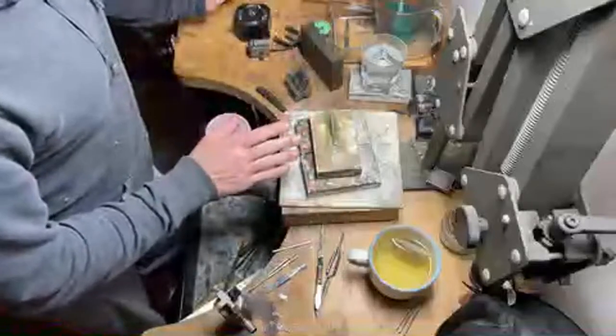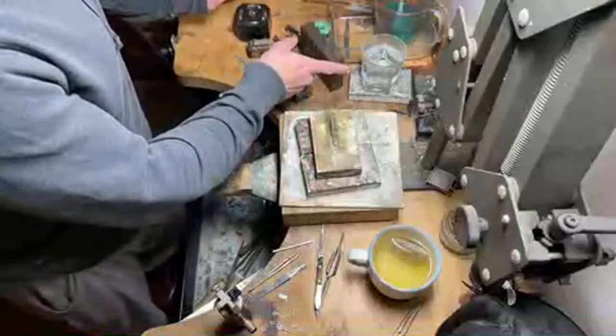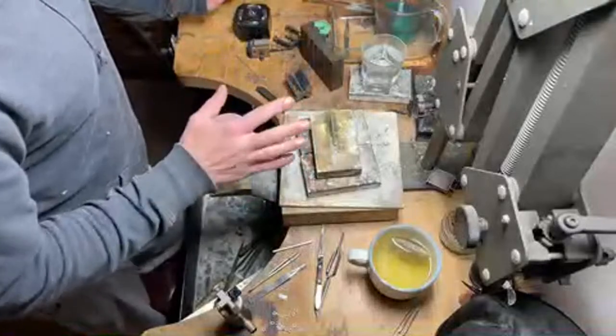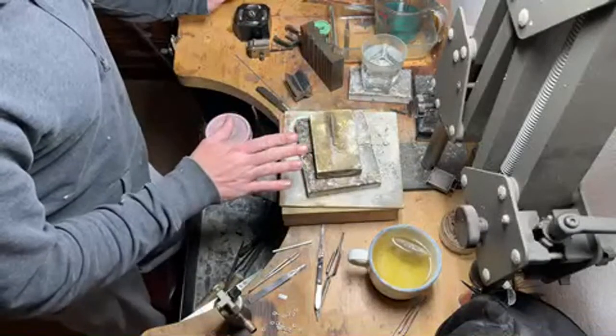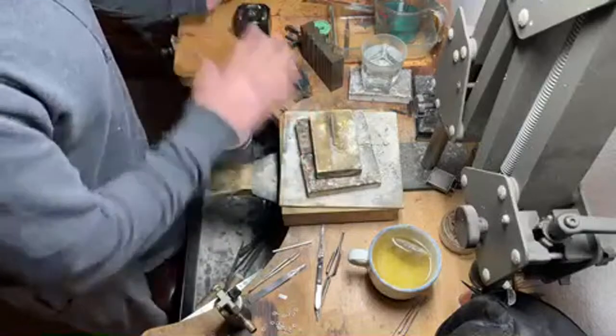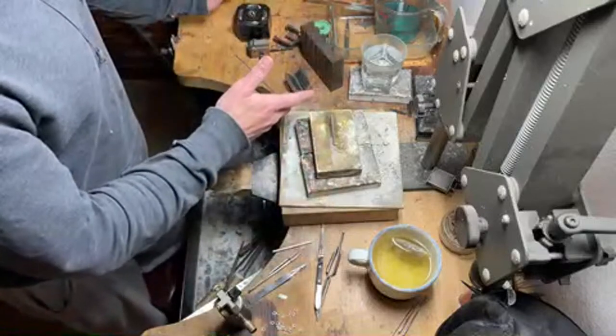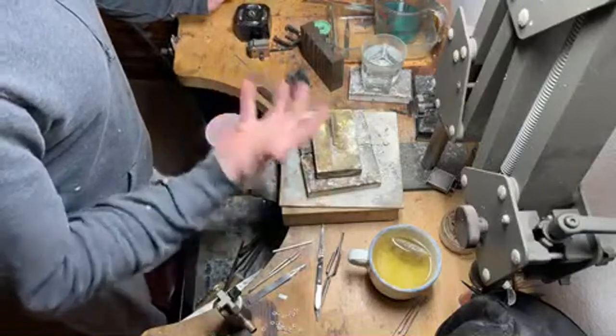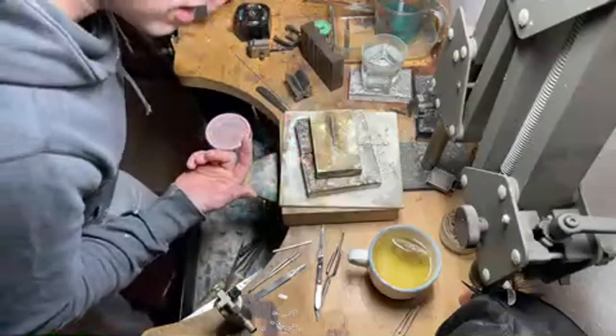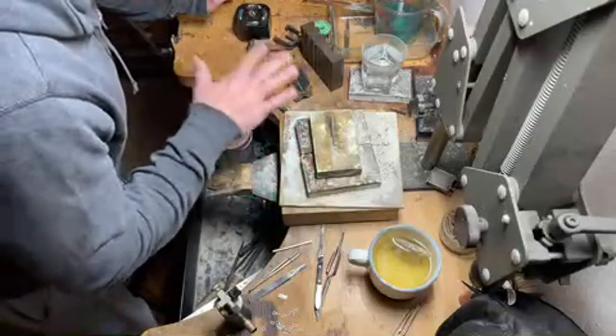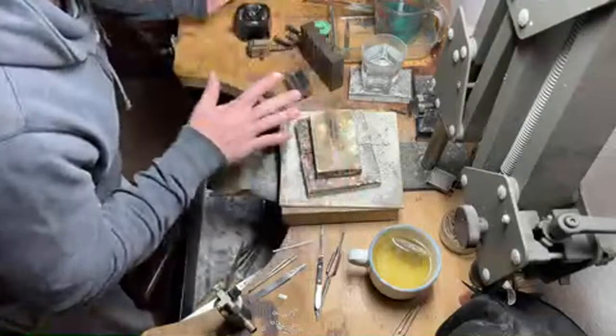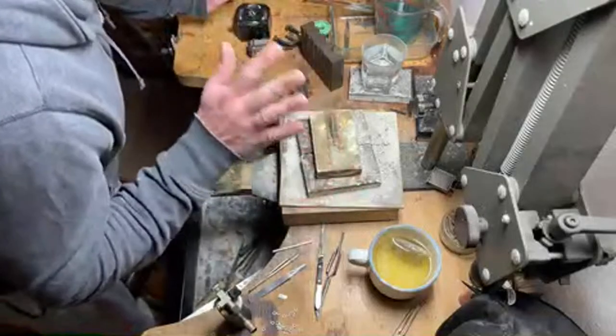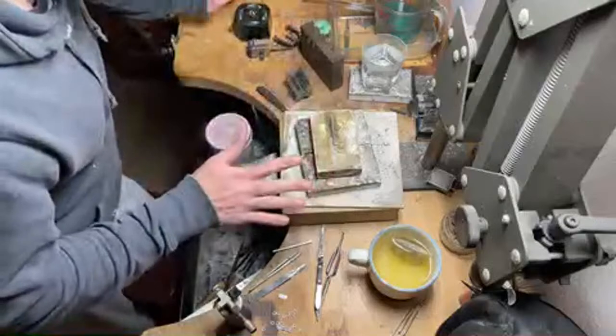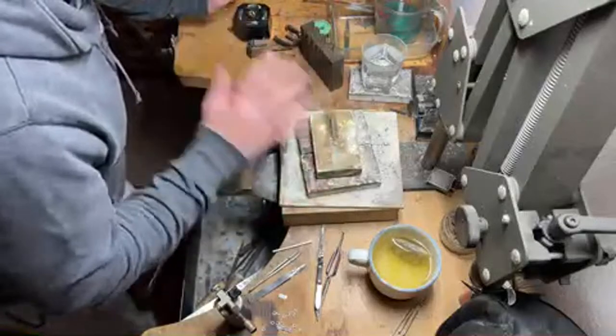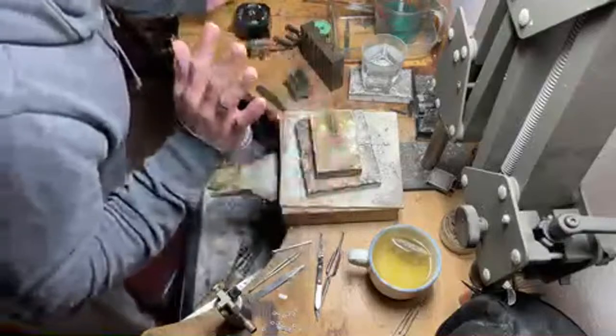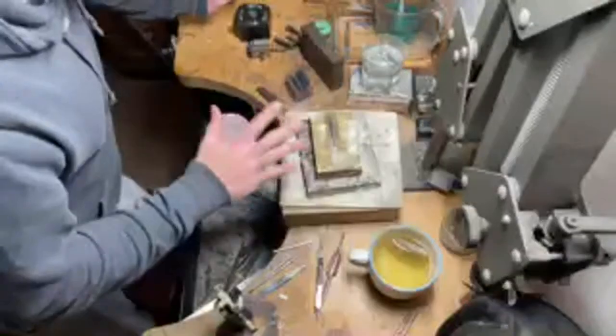I then let them cool down. Because we're going to quench it in the water while it's still hot, and then it will go in the pickle. I had some issues with silver, where I was quenching them too soon, I think. They were red hot, I was quenching them in the water, and it was almost like, a bit of an exaggeration, but when I was rolling it was like wringing out a sponge. I think whatever porosity was present was absorbing the water when it was going in there red hot, and it was causing bubbling and blistering. So now I don't quench them immediately while they're still red hot.